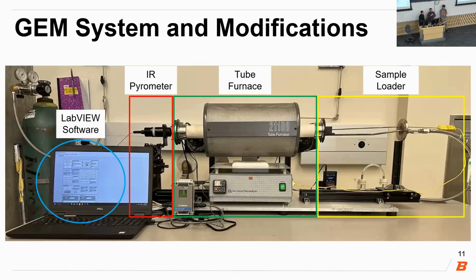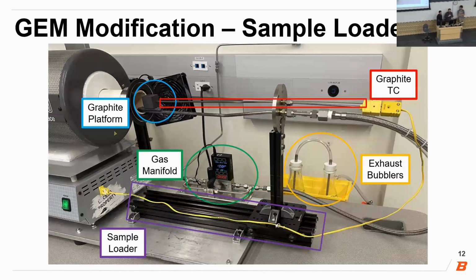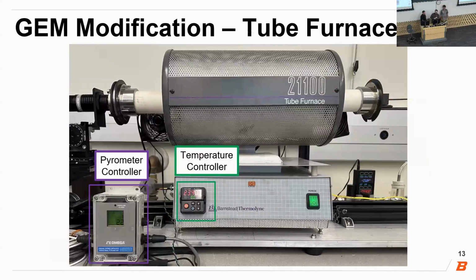So this is our GEM system. Essentially, at the start of the semester, we got this tube furnace. Here's our sample loader strategy. The sample loader was designed using extruded aluminum to ensure smooth movement in and out of the furnace. For our graphite platform, for that same reason, we need repeatable placement between samples within the furnace. That was a fixed position granted by our graphite TC. We also made changes to the gas manifold and exhaust bubbler.